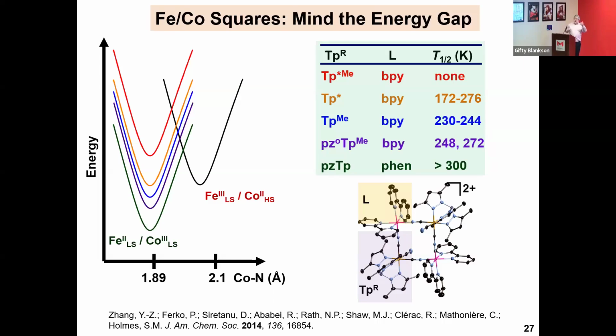And as you might imagine, can you go the opposite direction and get yourself into a hole again? Yes. If you have a very electron poor donor on iron and a very good electron donor on cobalt, phenanthroline, you're now in the opposite case. You're in this hole, can't climb out of it. Consequently, you don't see the electron transfer from the iron-2 to the cobalt. All right, and so as a general trend, as you decrease the donor on the iron, you increase the temperature where you see electron transfer. There's no mystery about it. It's just chemistry.